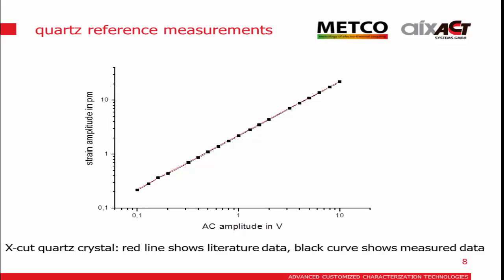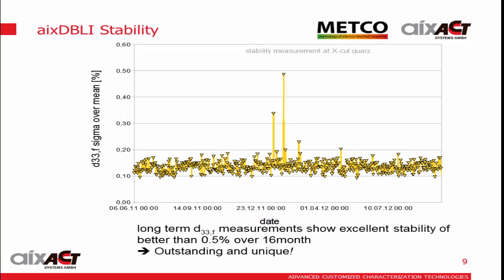What I could also show is the repeatability. Usually we take a couple of quartz measurements to monitor the stability of the system. This is data we took from an industrial system over, for example, 16 months, and we are still well below 0.5% repeatability in the measurement.